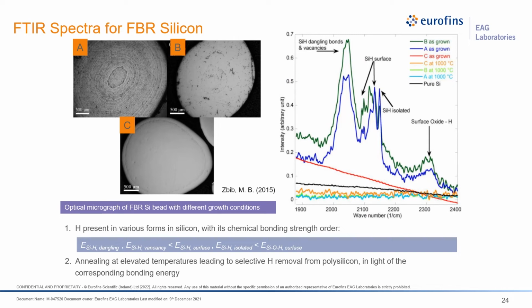Whereas for sample A and B, you can see a clear release of intensity where you can differentiate the release of silicon and hydrogen, specifically hydrogen, based on the bond energy difference for this different bonding. And by using this particular feature, we can probably try a fractional hydrogen analysis using IGA technique.